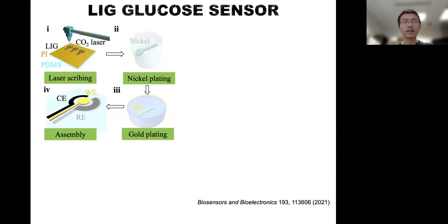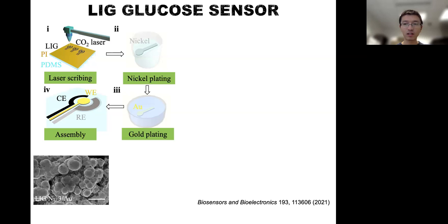On the other side, we can also detect glucose or other biomarkers from the sweat. And to do that, we have to do the electroplating process. And this is very challenging, to be honest, because the rough surface and the highly porous structure prevent a uniform coating. So the students here have tried different parameters and different processes to optimize everything so that we can still maintain the highly porous structure, but also create a rapid, uniform and sensitive coating layer. And here we use gold and nickel, and the compound provides a highly sensitive and selective detection of glucose. At the same time, it can be low cost from this electroplating process.